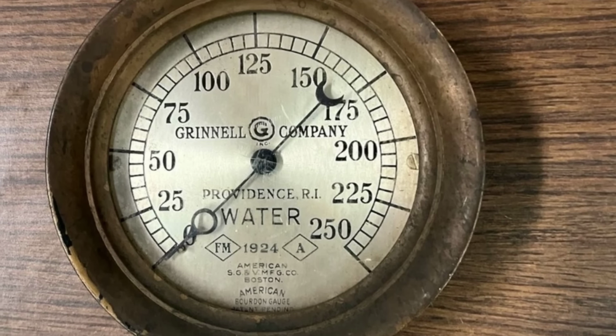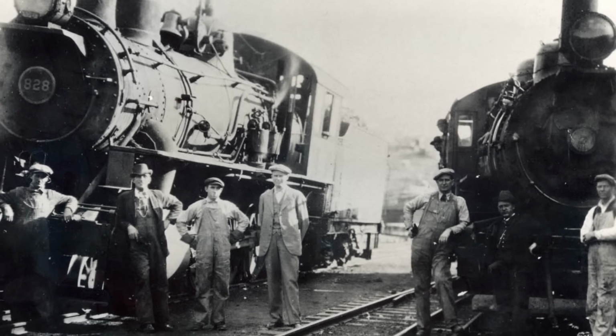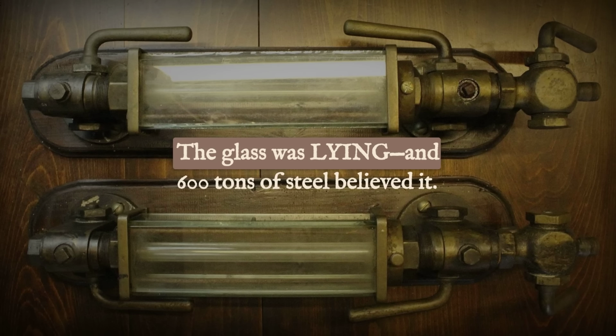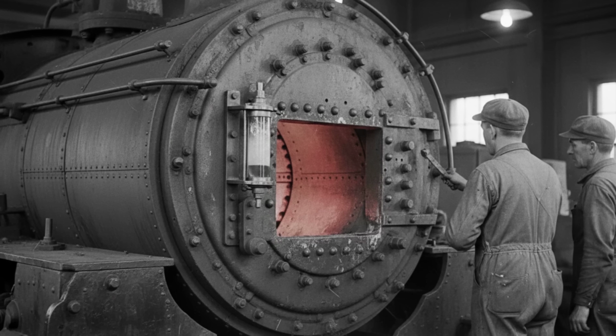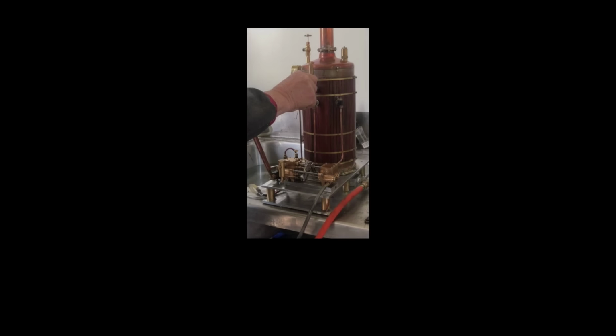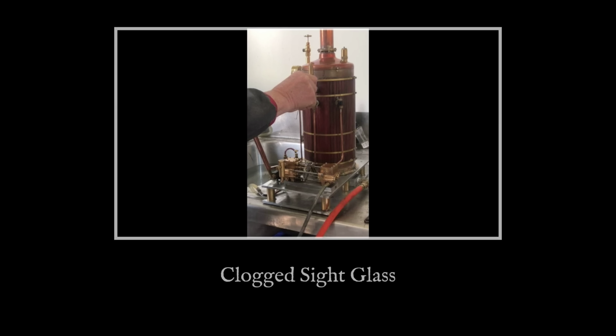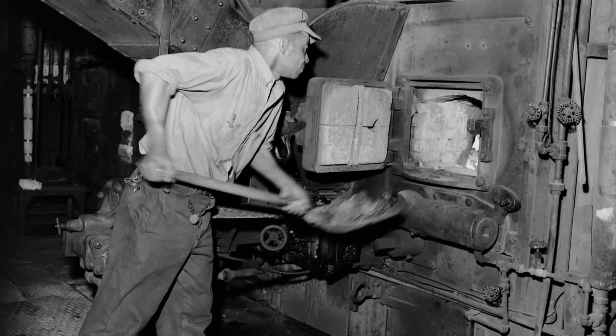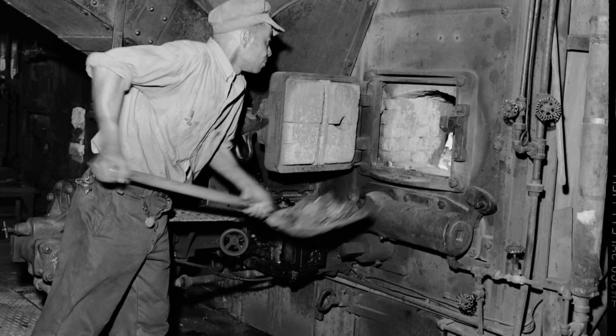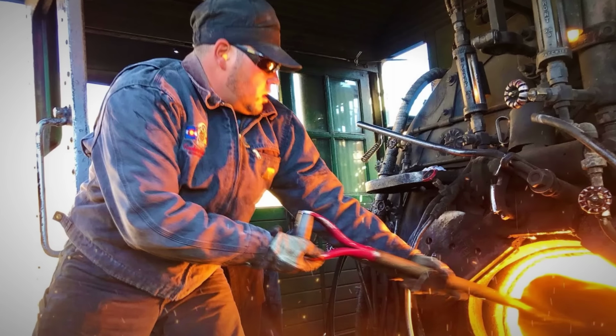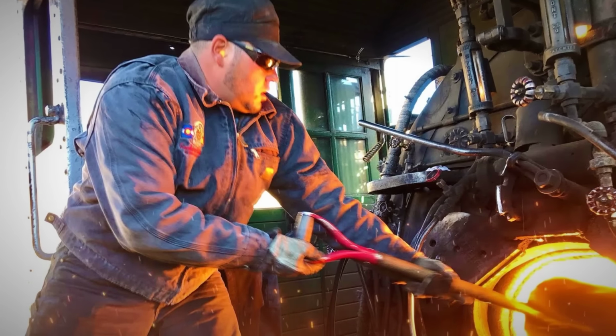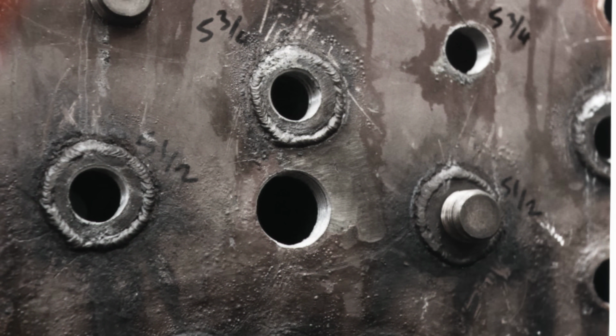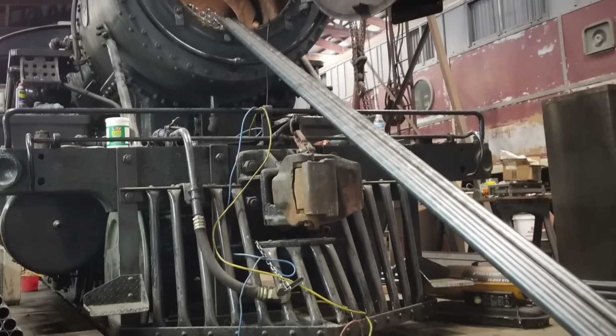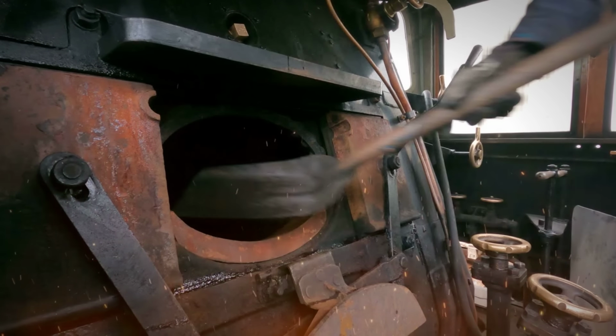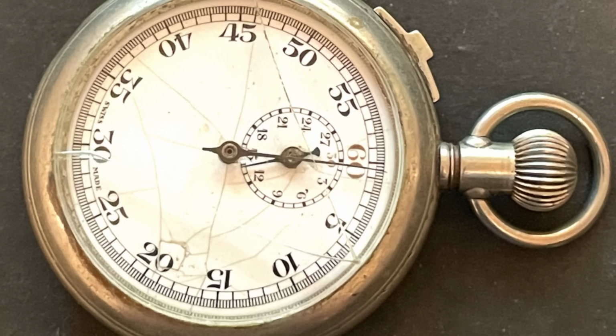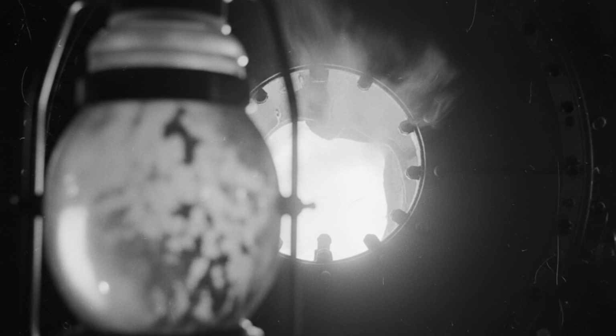When the crew checked the indicator, it read safe, water level steady, no cause for alarm. In reality, the glass was lying. The true waterline had dropped below the crown sheet, but the scale plug held a column of water in the tube, faking a normal reading. The engineer, trusting the instrument, kept the fire hot and the throttle wide. Behind the glass, the firebox raged at 2,200 degrees, and the uncooled crown sheet began to absorb the full blast. Steel that should have been protected by water was now taking heat direct from the furnace. Within 60 seconds, the temperature at the crown sheet soared past 1,000 degrees.